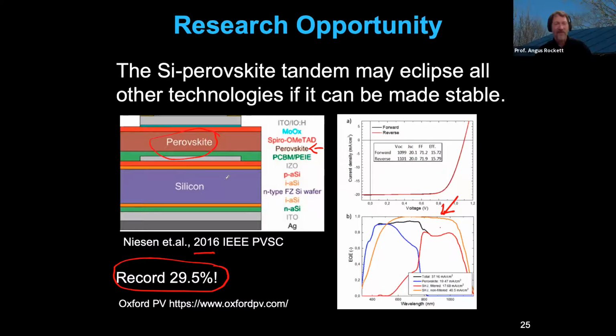If you can make the perovskite cell in the combination that I show here, if you can make that perovskite cell stable, yep, you will be able to make a fantastic module, because the champion device is almost 30% efficient. That's better than anybody has made in any single junction. And the perovskites are relatively easy to make. They're amazing materials, especially if you can combine them with something like spiro-OMeTAD or PCBM, something that you can evaporate or spin coat or whatever. Could be an extremely inexpensive and low-tech device to manufacture. Put it on top of your silicon device and there you go.